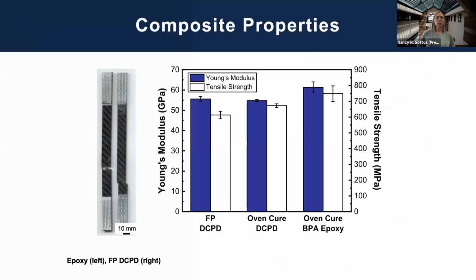So a little bit moving on to the properties of these composites. Again, we compared our composites to conventional autoclave cured epoxy composites for the same weave and same volume fractions. And again, you can see this is the frontally polymerized system, an oven cured system, and then a similarly oven cured BPA epoxy. And the properties are slightly lower of the composite for the DCPD than the epoxy material. And this is an area of where we're continuing to try to improve.